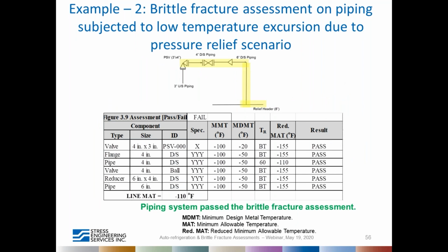Once again, API 579 or the design standards say that you have to consider every component and see if every component passes the assessment. So every component in that system is listed here, and it is compared against the minimum metal temperature or the CET. This is the original MDMT for that material. It is mostly impact tested, and then the reduced MAT based on the Level 2 assessment is shown here. For this example problem, this system passes because it is operating at a lower stress.